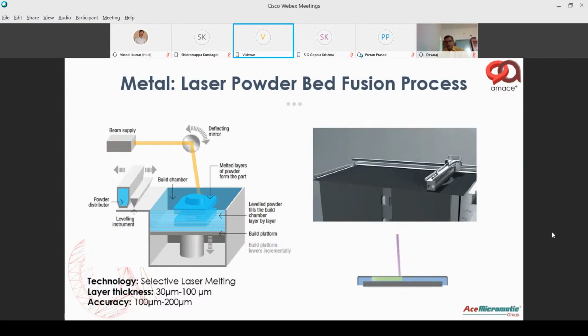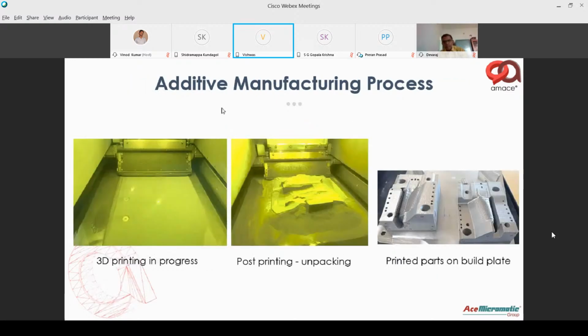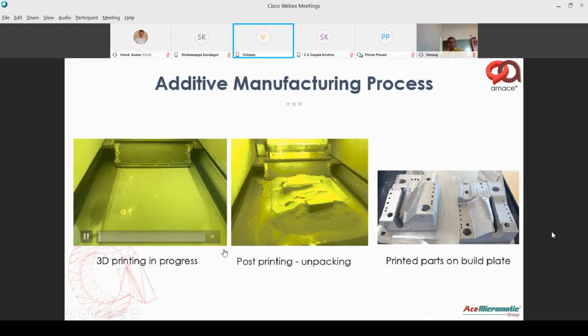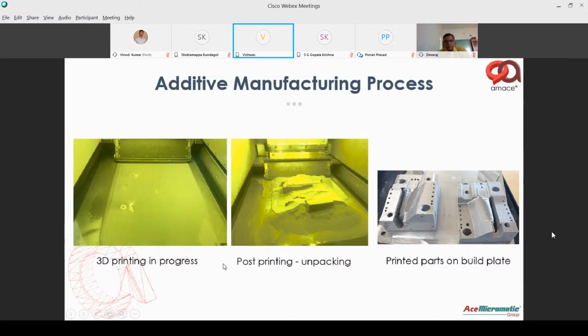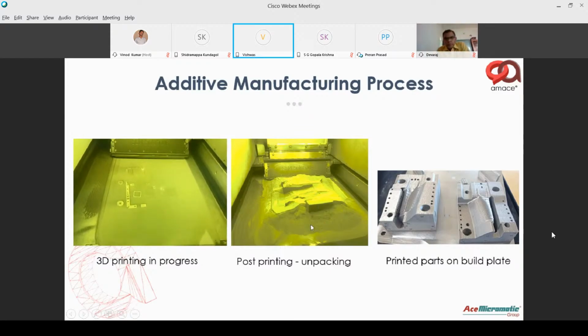Next, what we have going ahead is a demonstration of this printing process. There's a small video which shows you the 3D printing process. Here you can see there are two lasers printing two different parts. On the left side, the current layer of powder is being fused to the previously printed layer. As the printing process completes, the next layer of powder is laid. In the middle, what you see is an image of a part which is already printed. When we lift it up, you'll see the metal part is embedded in the middle of a big cake of powder.